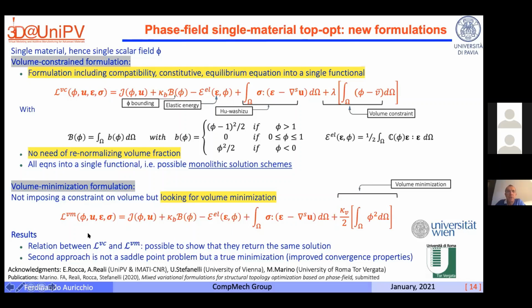So we come up with another formulation, which is down here, where you can see that the first part is identical to the previous one. So we minimize the compliance, we enforce one-shot equilibrium, but now we don't impose a volume constraint, but we impose a volume minimization. So we have a very standard volume constraint formulation, a very classical one, and now we have a new formulation, which is a volume minimization formulation.